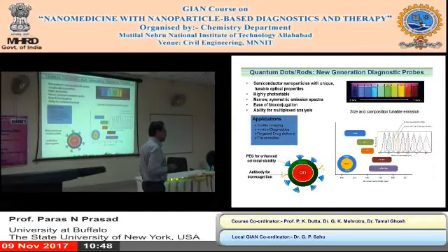because it protects the surface from deactivation. So if we use cadmium selenide, let's say, we will put a shell of zinc selenide. Light emitted here will not be absorbed by the shell. It comes out. And the shell's function is to protect it. Then we put a layer of organic like lysine, which is an amino acid, to make it dispersible in water.